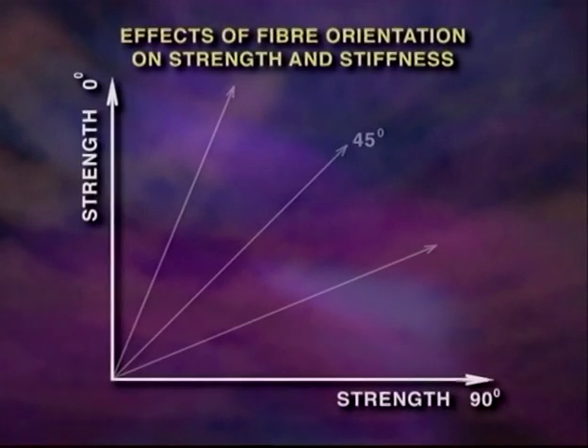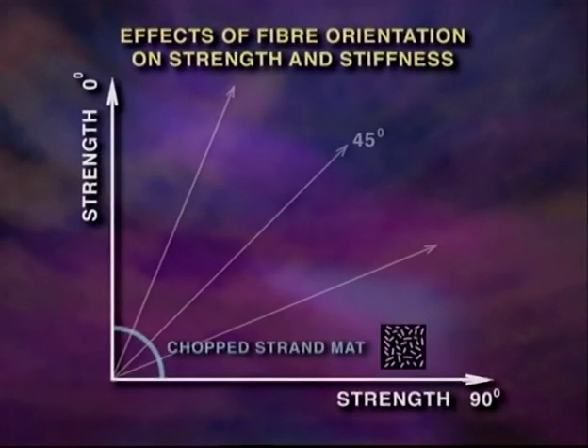If the strength of a material is plotted between 0 and 90 degrees, the strength of chopped strand mat is the same in all directions. Its strength is low because of the high percentage of resin, up to 70%. It is the fibres that give the composite its strength. For fibre content between 10 and 60%, the higher the fibre content, the stronger and stiffer the material.